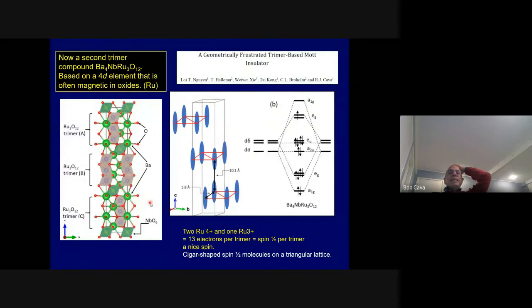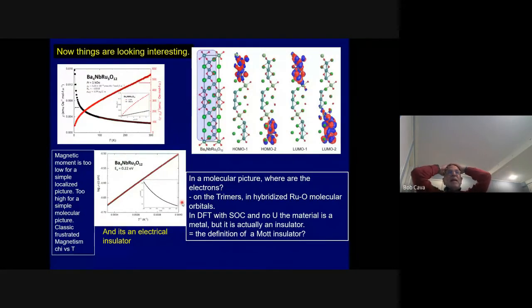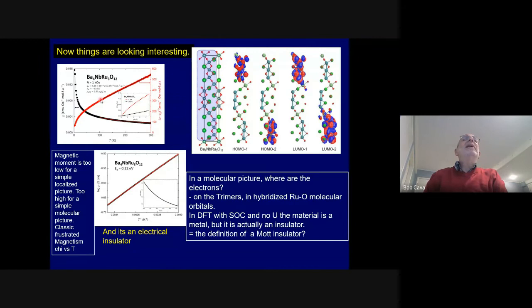And its magnetic susceptibility is starting to look interesting. Now you have barium 4, niobium, Ru3O12. When we look at the magnetic susceptibility as a function of temperature of this one, the intercept of this thing, which is the indication of the strength of the magnetic interactions, is around 150 Kelvin. And it doesn't magnetically order. What? So it did something crazy already.